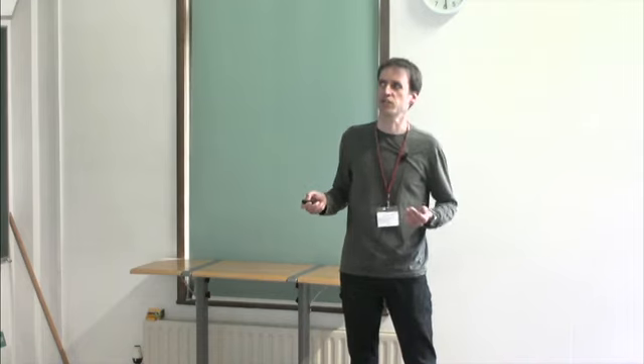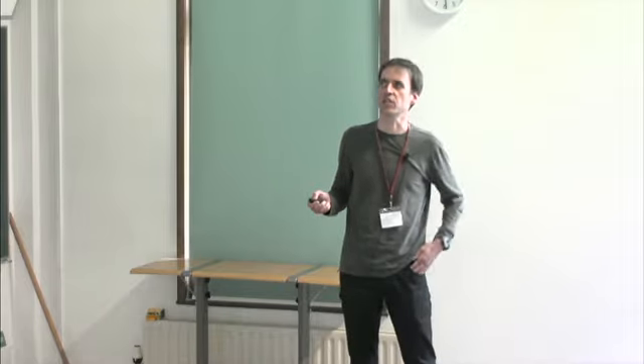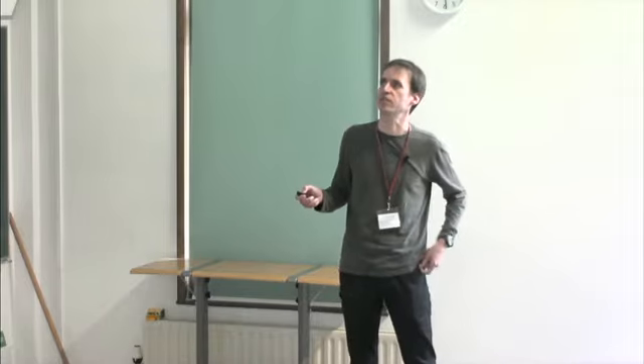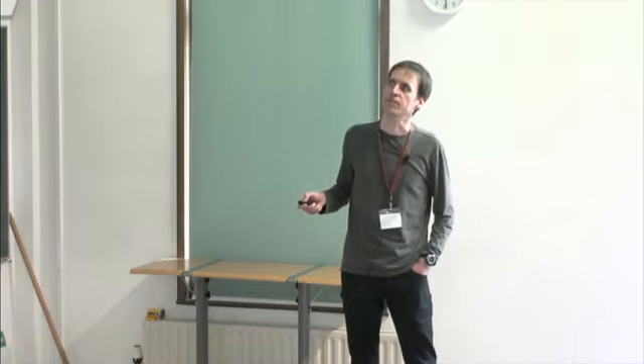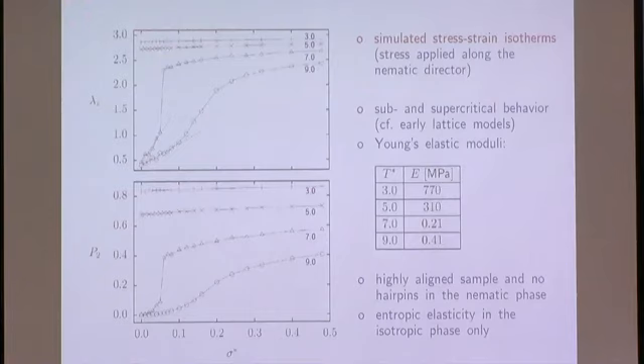In the isotropic phase, the polymer chains are able to explore phase space better than once they are already aligned. It seems that we have this entropic elasticity only in the isotropic phase. In the nematic phase, this entropic elasticity could have been recovered if we had so-called hairpins in our system. But on average, we have a rather short crosslink to crosslink distance, just 8 units, and hairpins are not very probable in our systems.